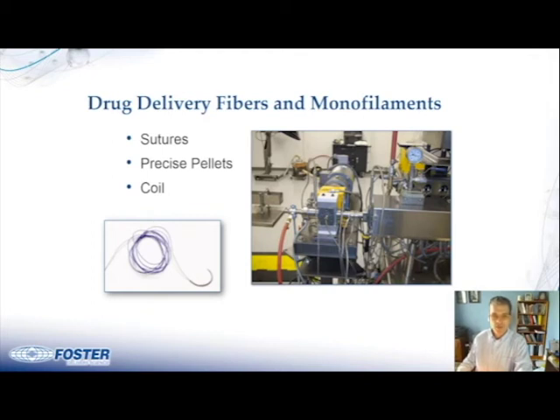What's shown in the picture here is a twin screw extruder, and there's a vacuum vent, so where we're controlling the vacuum that's being applied to the process. And at the end of the machine is this melt pump. So we have an inlet and we have a melt pump or a gear pump that's increasing the pressure and stabilizing the pressure that's coming from the twin screw. And then there's a die on the other side going through a cooling device, and then the product is cooled.